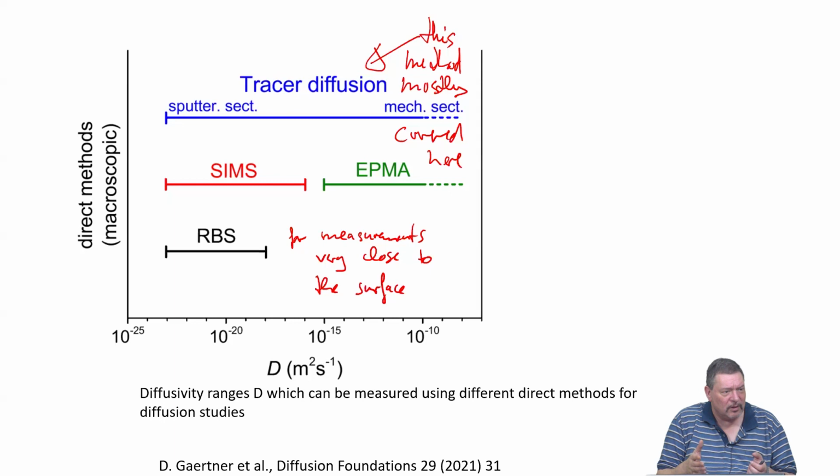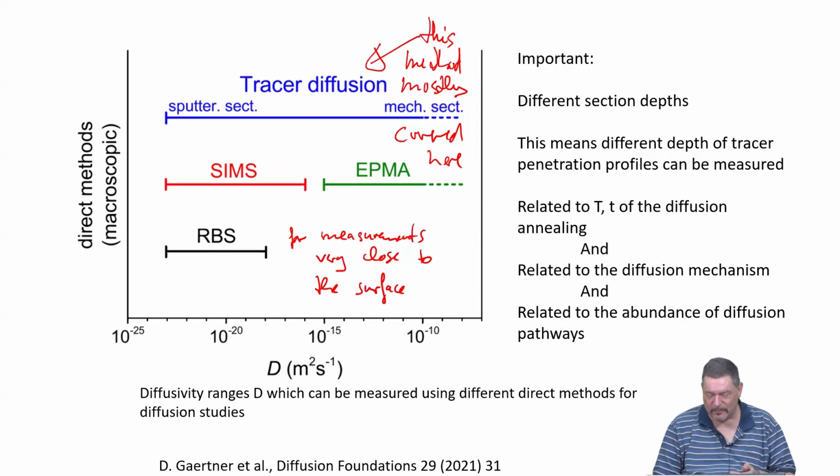And typically, what you have to do is wait maybe between something like a day up to 4 weeks of one slice in the detector to get enough counting efficiency to have sufficient signal to noise ratio. More is more or less just not done because so many people want to use the detectors and it just cannot take years or so to count, right? It's just a practical limitation.